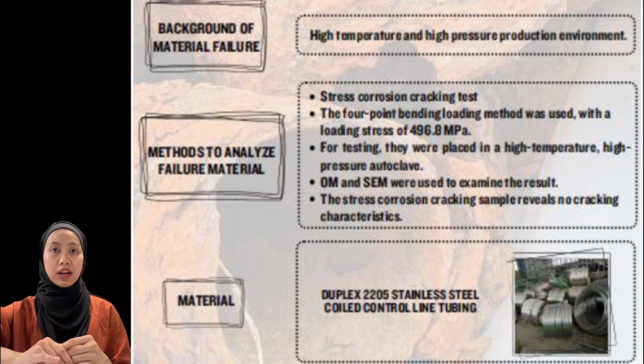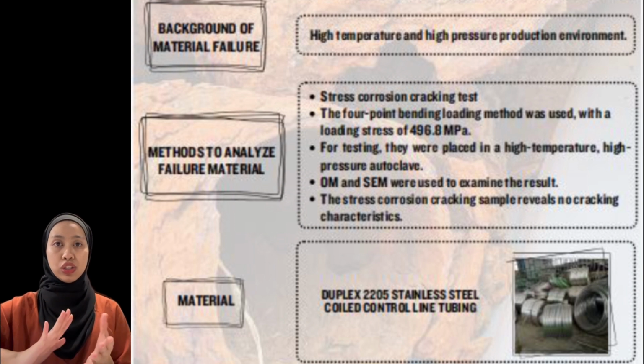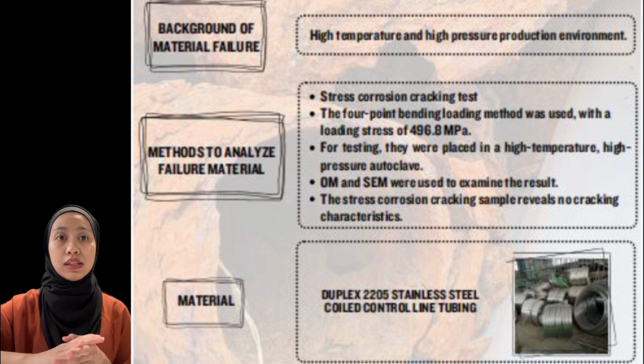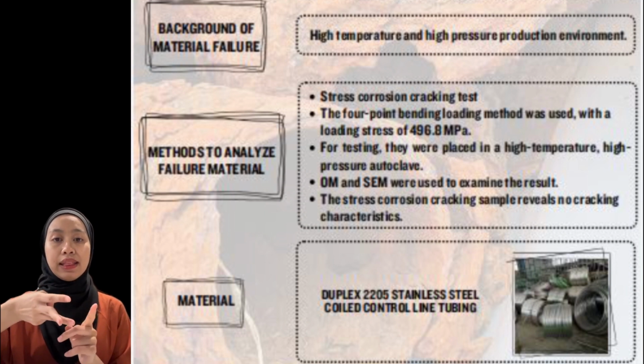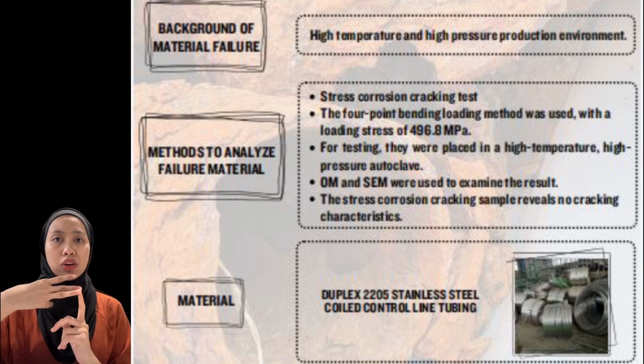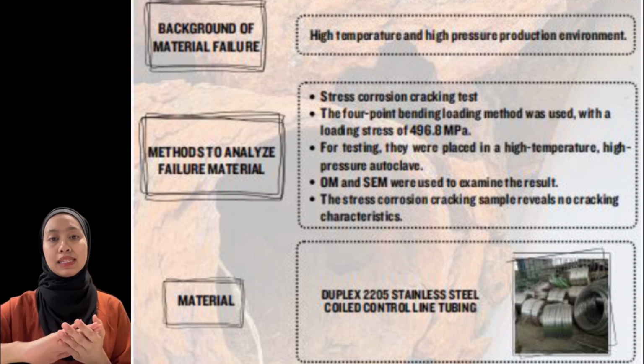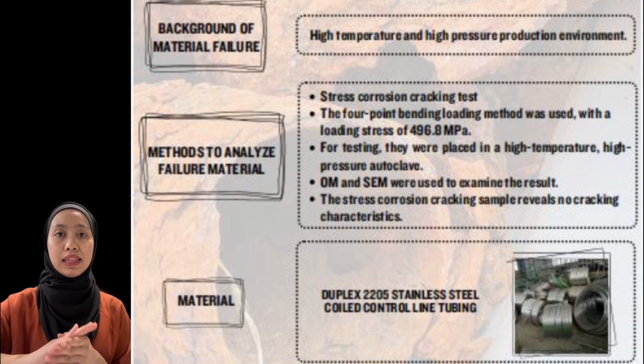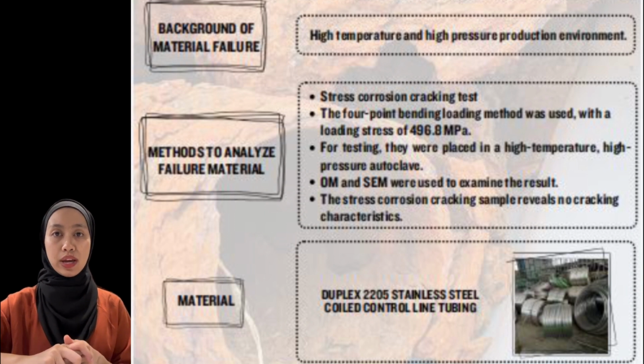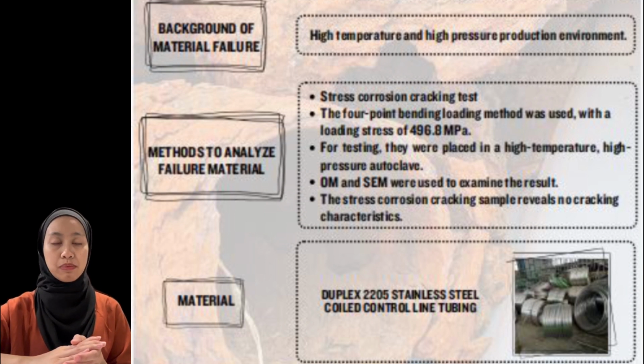This SCC test in the production environment was conducted by the four-point bending loading method with a loading stress of 496.8 megapascal. Then the loaded samples were put in a high temperature and high pressure autoclave for testing. The test conditions, including the test solution, carbon dioxide and hydrogen sulfide partial pressure, total pressure, and test time, are the same as the corrosion weight loss test in the production environment. After the SCC test, the longitudinal sectional morphology of the maximum stress area of the sample was observed by optical microscope and scanning electron microscope.